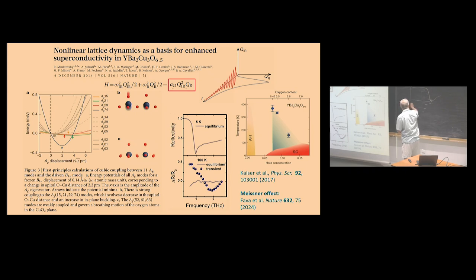Also, the optical conductivity looks like this. This is Drude conductivity. You have Drude conductivity, and then it decreases close to the plasma frequency. But what happens at the superconducting phase transition? You have, let's say, the band gap, I mean, the energy of pairing of Cooper pairs, let's say here, which can be somewhere around 1 terahertz.